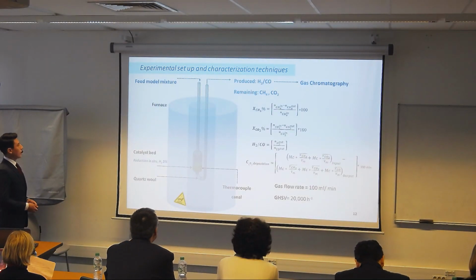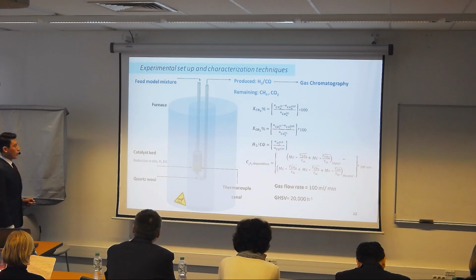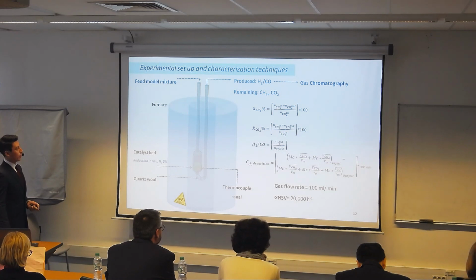The reactions were made in a fixed bed reactor. We deposit the catalyst bed here. They were reduced in situ at 800 degrees. And the final compositions coming out from the reaction were measured by gas chromatography.